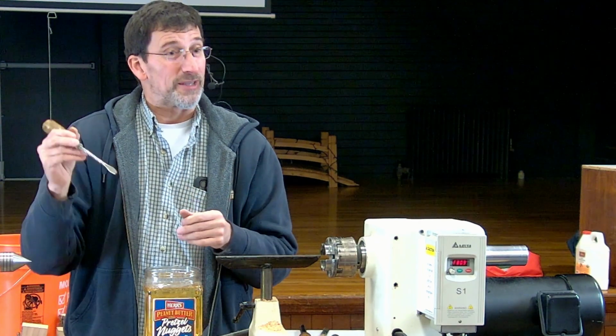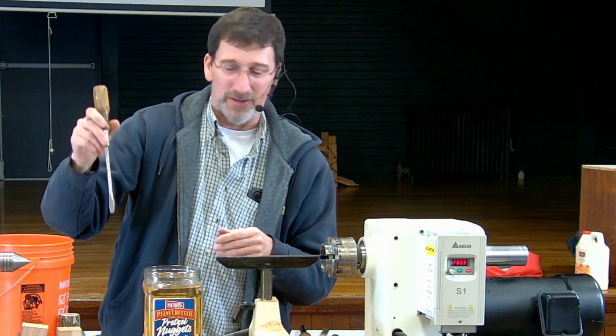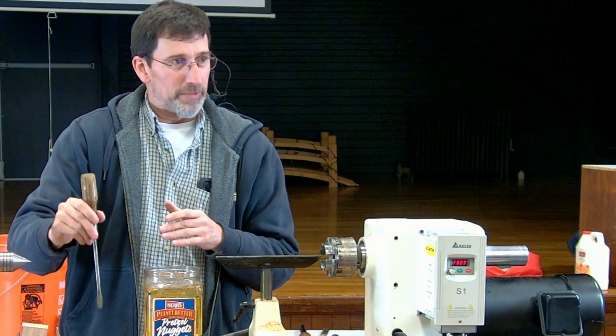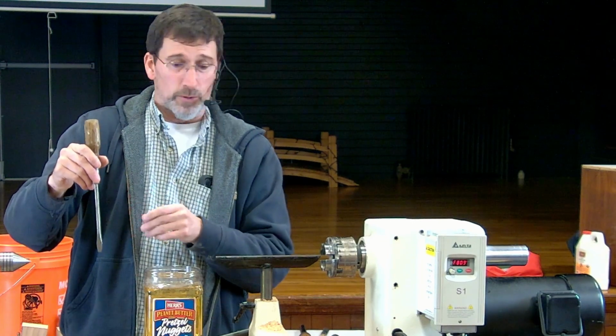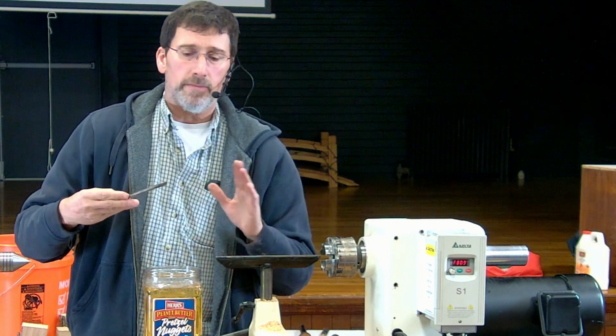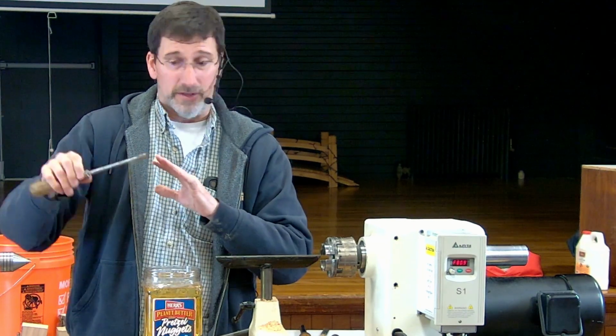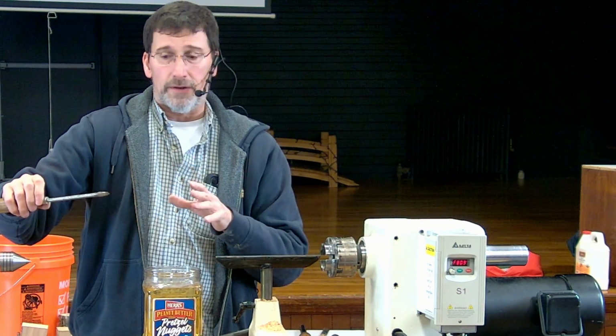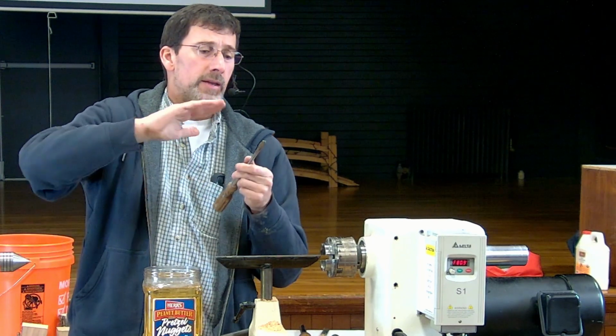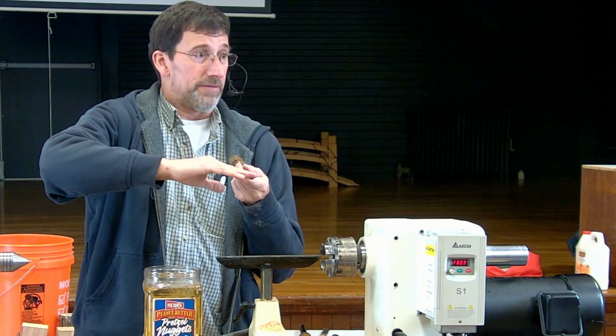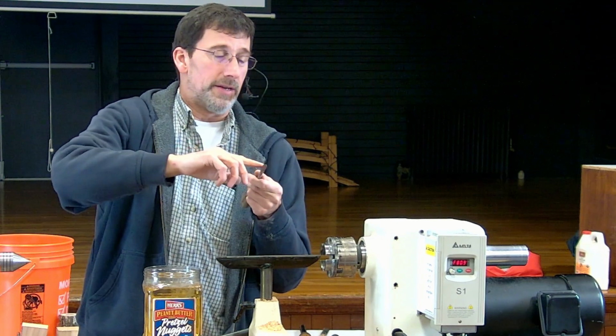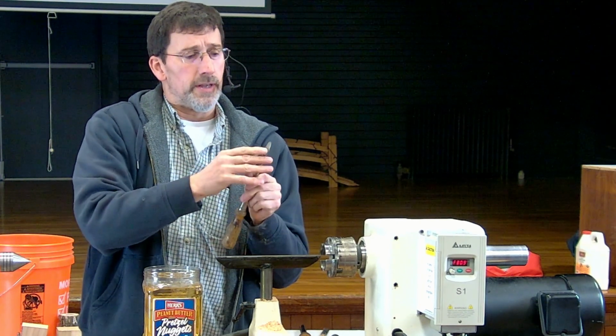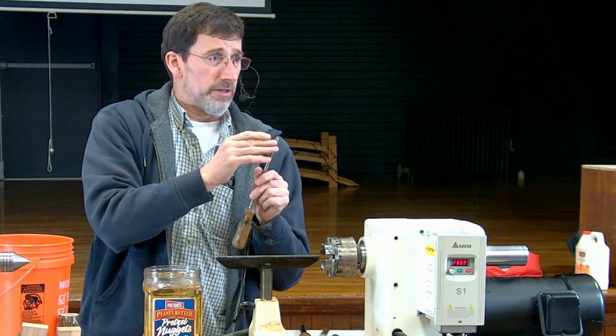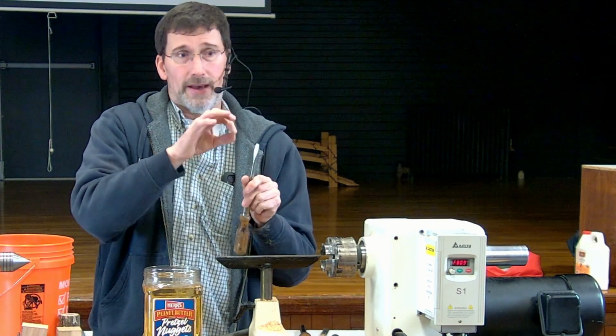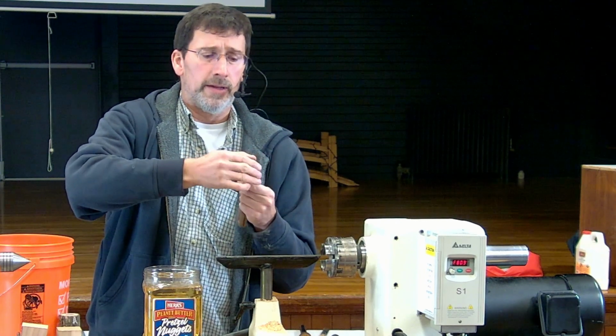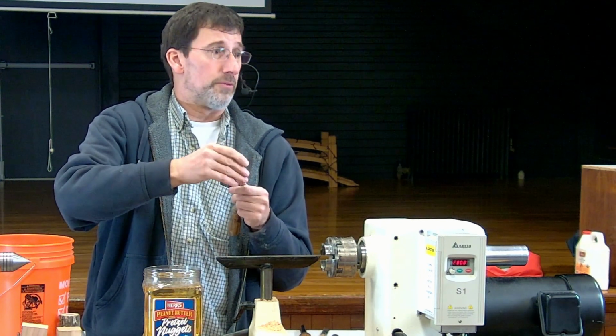It's pretty hard to guess when you get to that point. So I typically just keep it in until it's relatively cool. When you take it out, it's still hot. Don't try to touch it. Set it down, wait a few minutes, wipe it off, sand it to a bright finish, and then heat it again. And I recommend heating it till you get the straw color tint. And that will make sure that it's not too brittle, but it's still relatively hard.